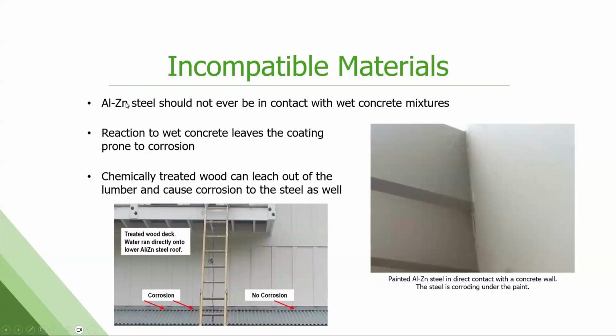You cannot put the aluminum zinc substrate in direct contact with wet concrete mixtures. You've got to have a water vapor barrier. Otherwise, this is a concrete wall on the right, metal panels on the left. They did not put a vapor or water barrier in there, and it's causing the paint to peel off the metal panels due to the moisture content from the concrete.